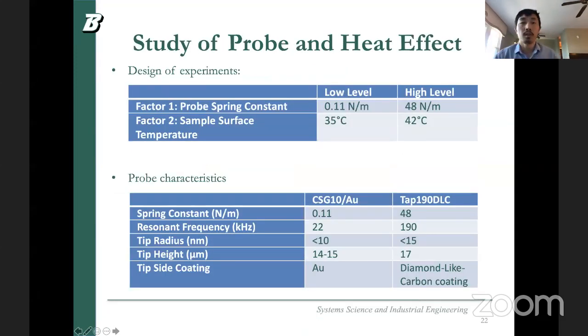With all those interests, we want to know why we cannot use the stiff probe, because at the very beginning we tried to use the same probe as we used for the vibration-only assisted nanomanufacturing process. But it turns out the trenches get very deep because the PMMA becomes soft with the elevated temperature. So we designed experiments to see how the probe actually affects the features.